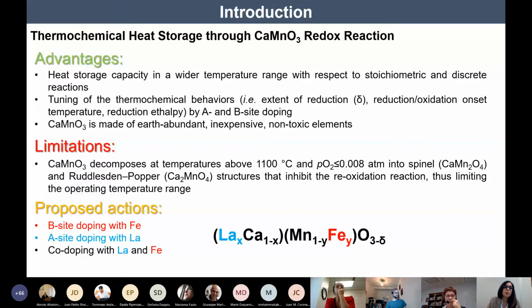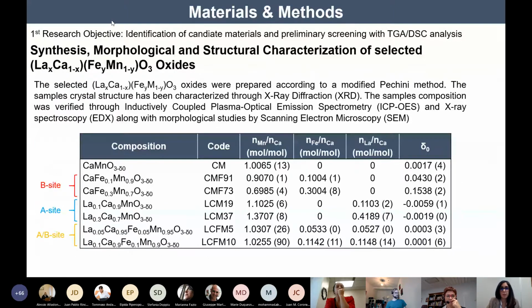The first research objective of this study consisted of the identification of candidate materials and their screening with TGA DSC analysis, in order to determine which could be the suitable compositions for this application. We ended up with the list reported in the table, with 10% and 30% iron doped and lanthanum doped compositions, but also 5% and 10% co-doped materials.